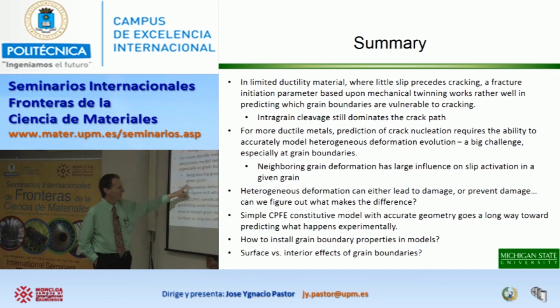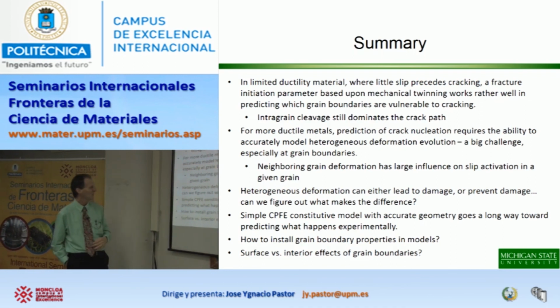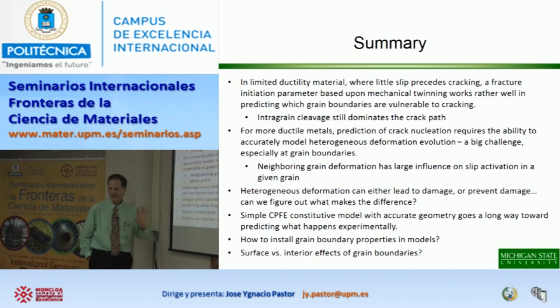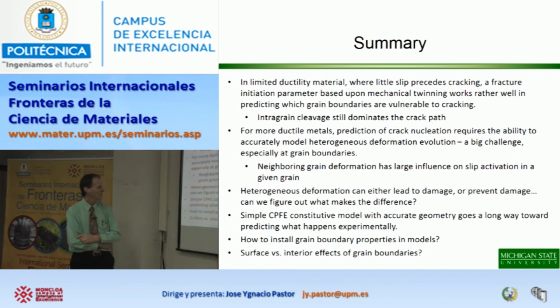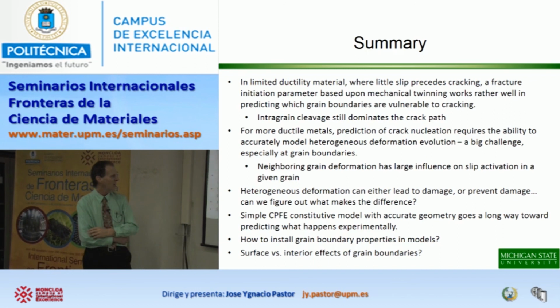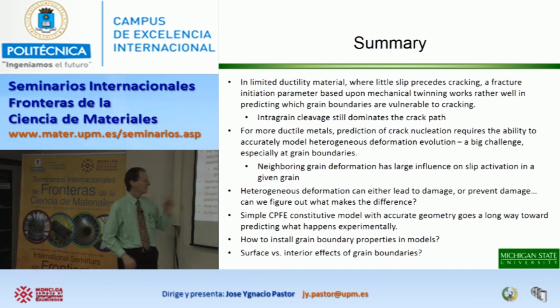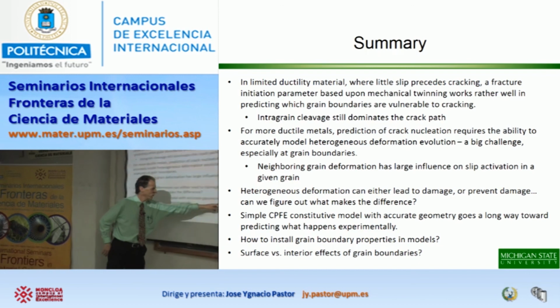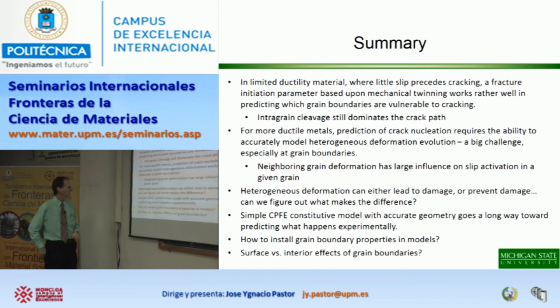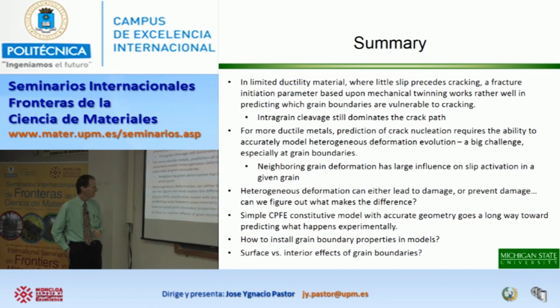So clearly, all the neighboring grain deformation has a huge influence on how slip occurs in any given grain. And heterogeneous deformation can either lead to damage or prevent damage, but can we figure out what makes the difference between what helps and what doesn't? And a relatively simple computational model, now I say relatively simple, the math of the hardening process is what's simple. There's lots of things we could do that are more complicated. But the key thing is with accurate geometry, we can go a long way toward predicting what really happens experimentally.